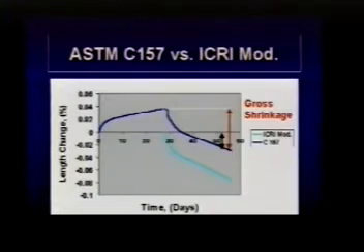This is a plot of length change versus time for the 2 test methods. In the dark blue is the C157 length change curve. And the turquoise is the ICRI modification of that version. And I've shifted that over so that we can see how the shrinkage profiles are very similar. In 2 terms, the black arrow would represent the shrinkage that is reported by the C157 test method. However, what's more important to look at is what I'm going to call the gross shrinkage. And this is the difference between the peak of expansion of the 157 method and the lowest shrinkage that is observed.